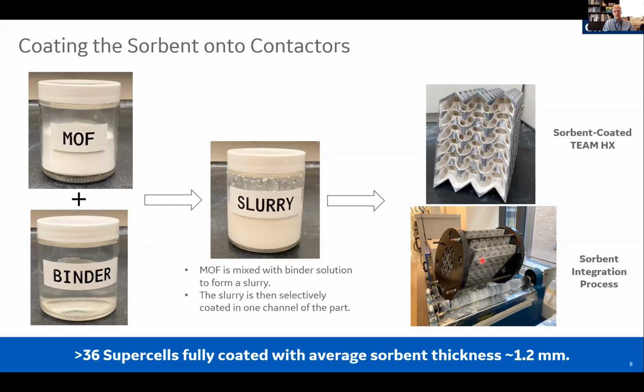Here's just one way that we do the sorbent integration process. We can modulate the thickness of the coating that goes onto these devices, and we can scale this across a number of different types of contactors. So here is one type of contactor that we've developed, and then we can coat this, and that fits in the palm of my hand. We've scaled that up to these much larger sizes. So you can see this here.